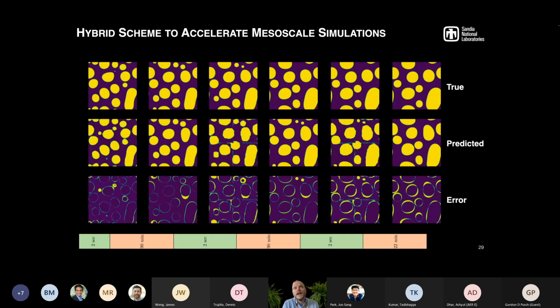One of the hybrid schemes that we came up with is as follows. You can run your machine learned engine for a number of seconds. In this case, that would be 2 seconds, which corresponds to predicting about 20 time frames, and then feed it back into your direct numerical simulation to again simulate 20 time frames, and back and forth. And so what you see here is that you can leap in time that way.